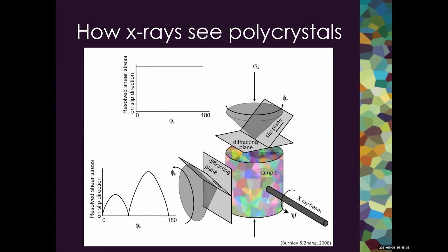So the population of grains that are in the X-ray diffraction peaks aren't completely homogeneous depending on where we look at them. This diagram is just showing the relationship between the diffraction geometry for grains contributing to a given lattice reflection and the orientation of slip within those grains. And so for diffraction in the compression direction, all grains contributing to a lattice reflection will experience the same resolved shear stress because the angle between the slip plane and the loading direction is going to be constant. But for diffraction in the transverse direction, the group of grains that are selected by diffraction to be in the same diffraction peak can actually have a variety of resolved shear stresses.